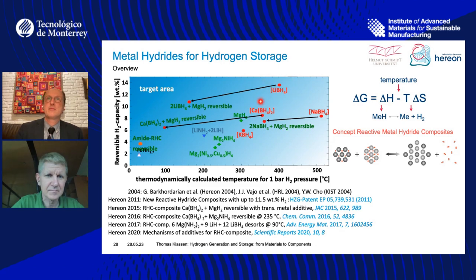There were some hydrides like lithium borohydride with almost, if you take all the hydrogen out, you would get to 19% weight, very high. But usually you are left with lithium hydride and you can't split that. And this is why here it's at 13.5, but you have to go to 400 degrees to get it out. And it's not reversible. So this is why it's in brackets, because it forms some structures that don't form the lithium boron bond later again. So the boron 6 cage is quite stable.